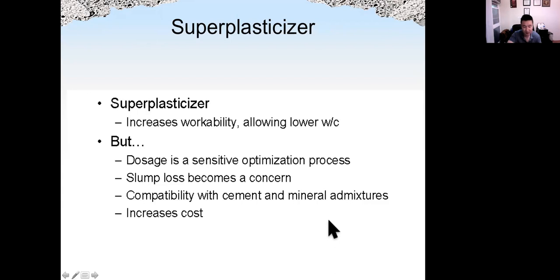For superplasticizer, it will increase workability, so we can allow a lower water cement ratio. It is essential for high strength concrete. Dosage, how much you use, is very sensitive. And slump loss, which is loss of slump of concrete over time, is a potential concern when we use superplasticizer. And also sometimes we have so-called compatibility problems with cement and other types of admixtures.